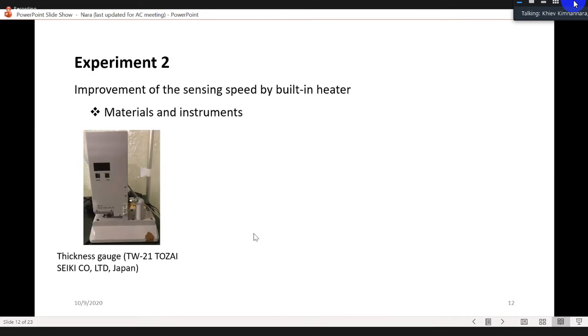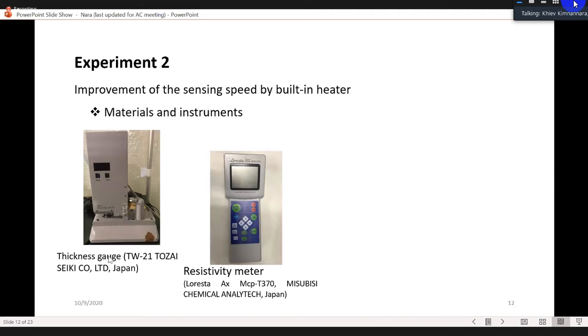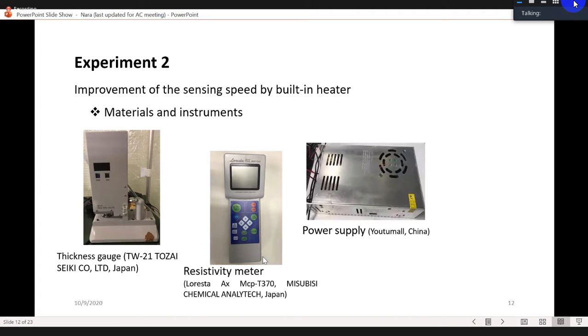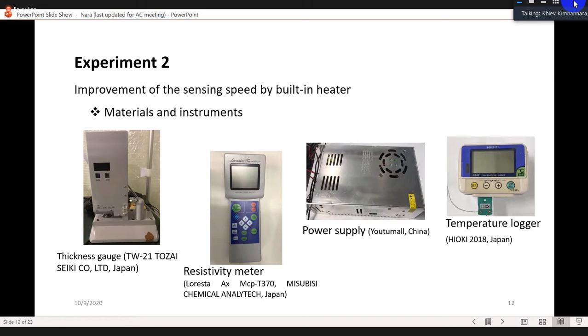Materials and methods. In order to measure the thickness of the CNT layer, a thickness gauge was used. Then I used the resistivity meter to measure the resistance of the CNT heater. After that, a power supply was used as the main material to generate heat. And then a temperature logger was used to measure the temperature changes or the temperature increase.